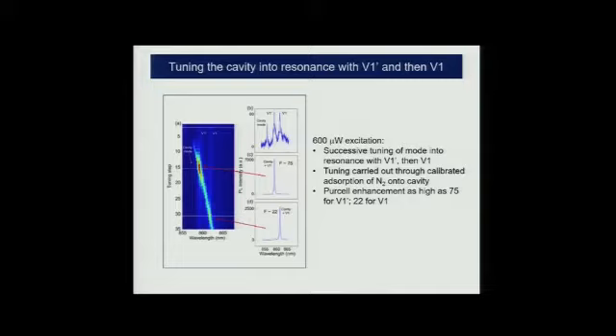until first the cavity mode comes into resonance with V1 prime, and we see a dramatic increase in the intensity of that transition by a factor of 75. Then we continue to tune that cavity response until it comes into resonance with V1, and we see an increased intensity of a factor of 22. So when we tune this lens and finally focus it, we see a lot more detail about these two transitions that are very much related.